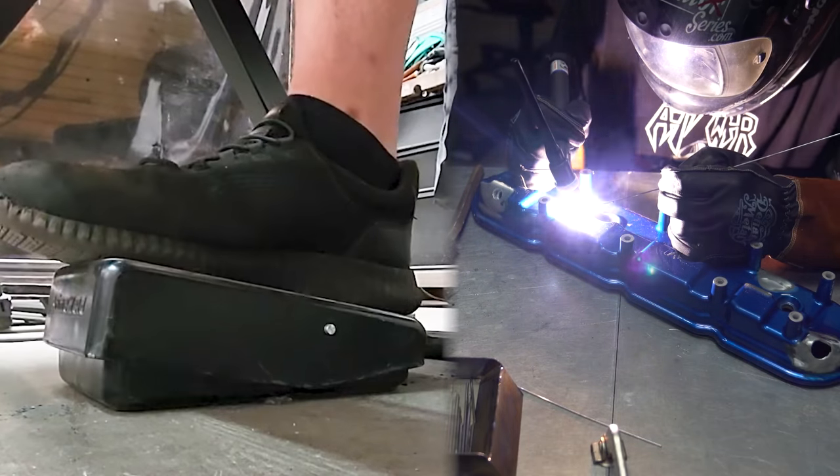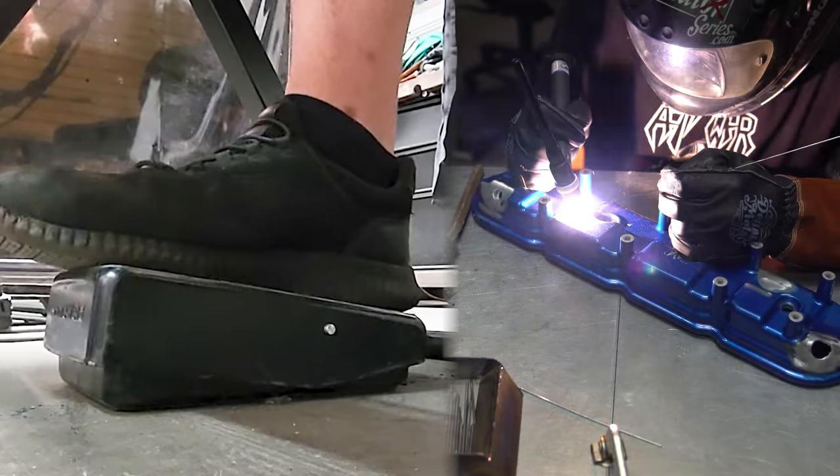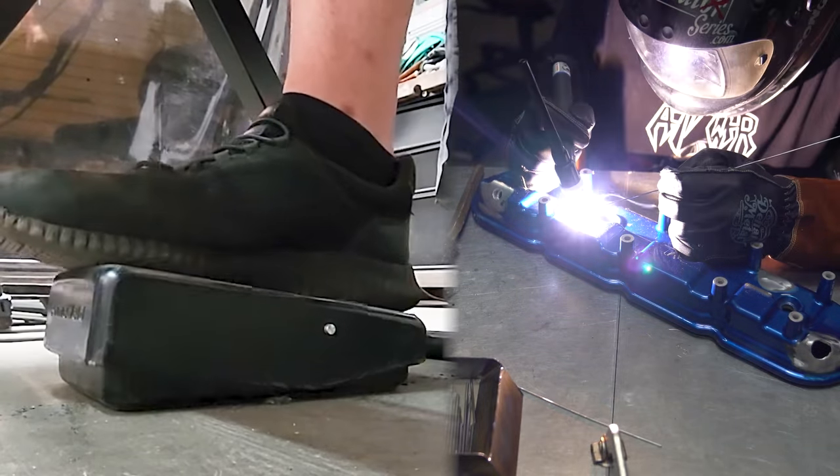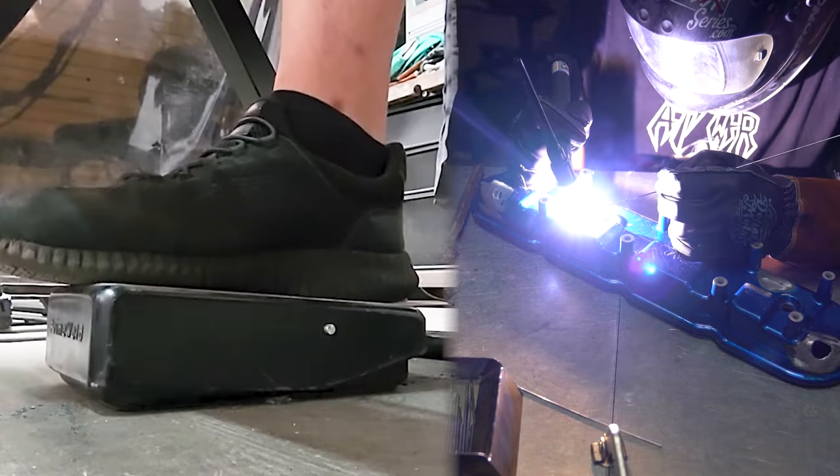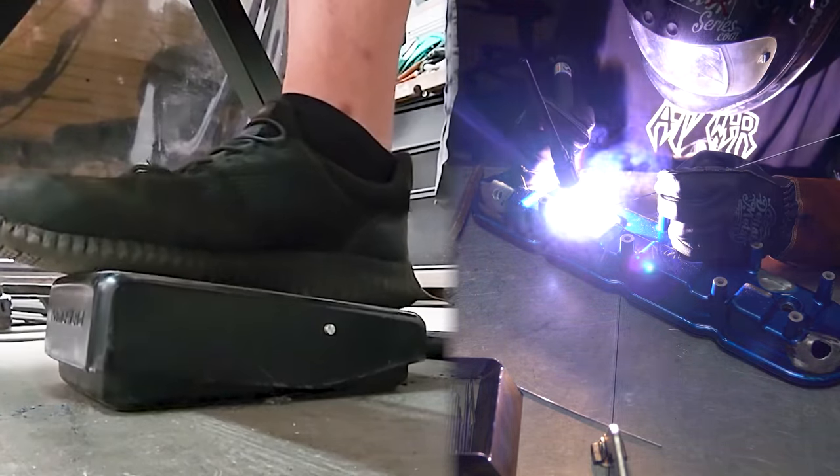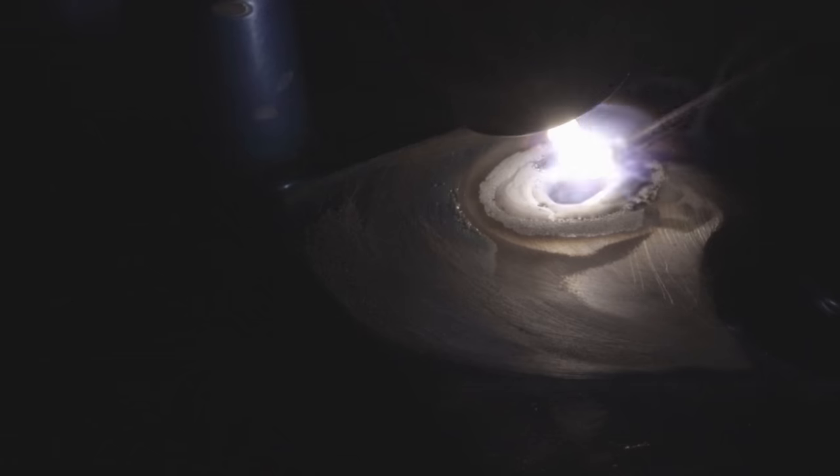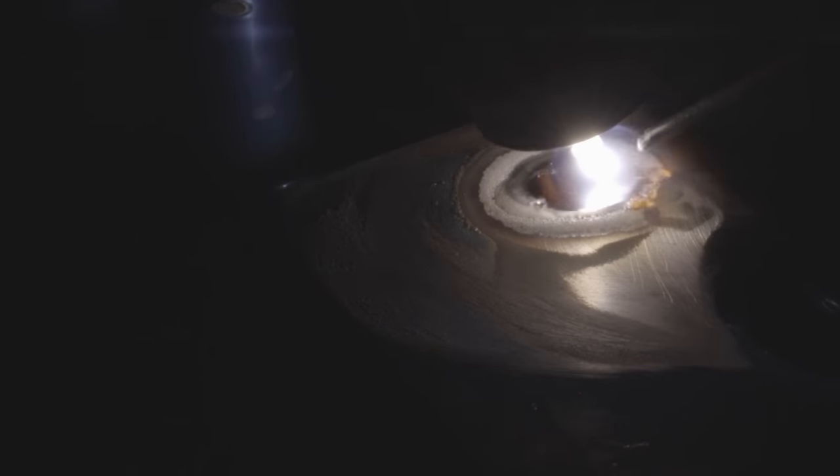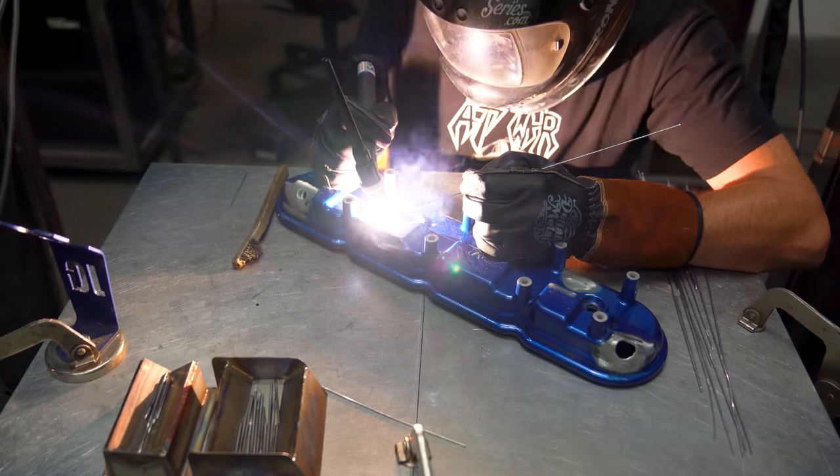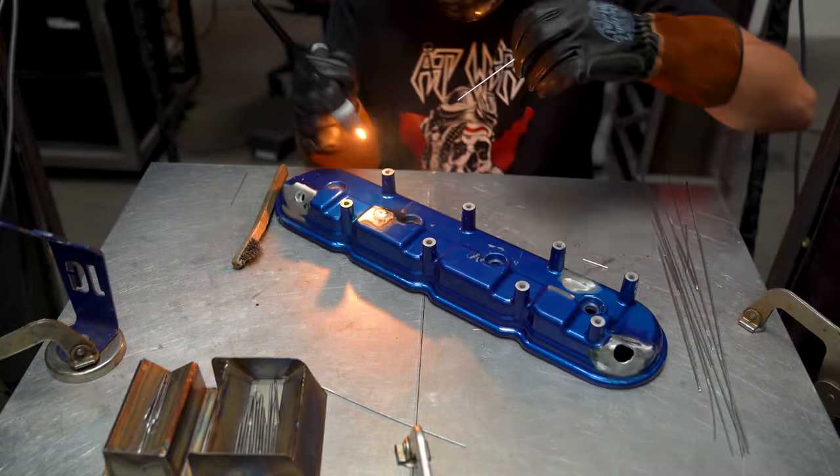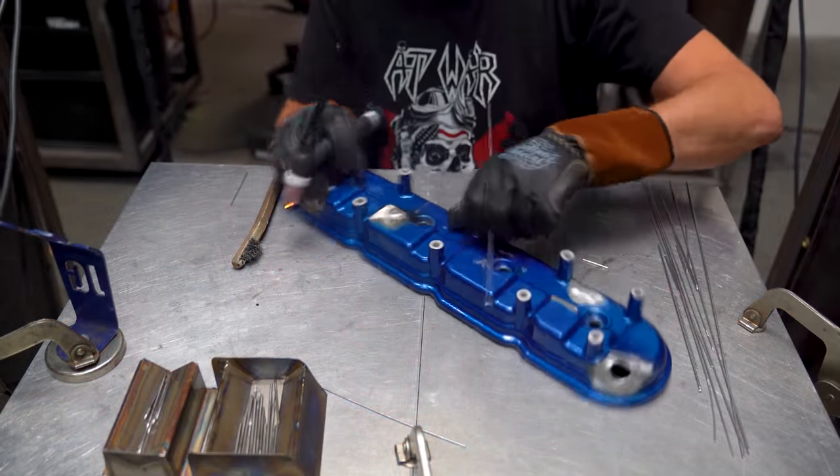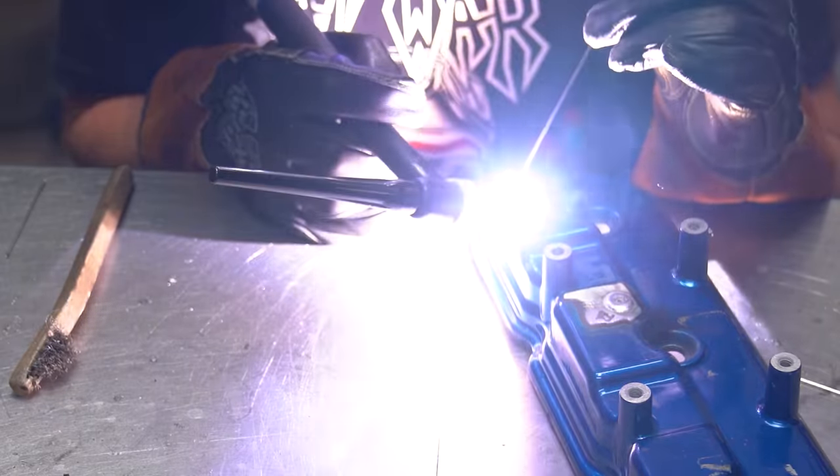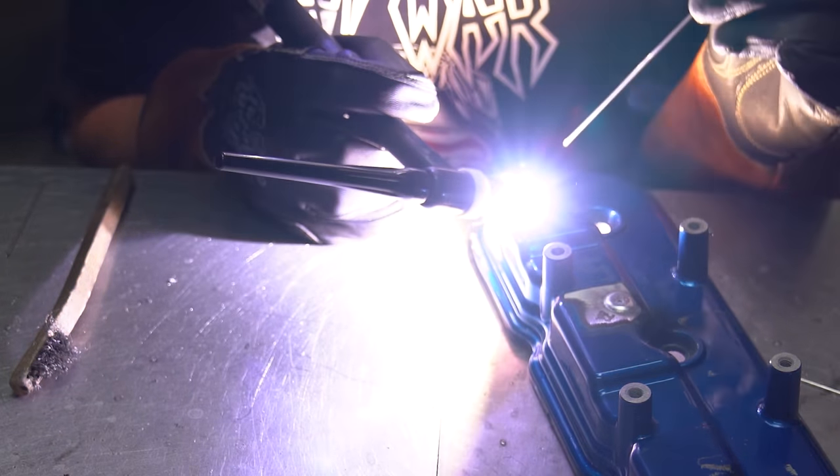Welding holes can be super easy or super tough, depending on the person and your experience level. The trick here is to read the pool and understand that you are the one who's in control of the machine. Ideally, you're going to use just enough amps via the foot pedal to control what the metal is actually doing. You need just enough to keep the edges molten while you add a small drop of filler. Not to be confused with just throwing a clump in there or stuffing the filler in there hoping that everything goes swimmingly. You need just enough. So how much is just enough?